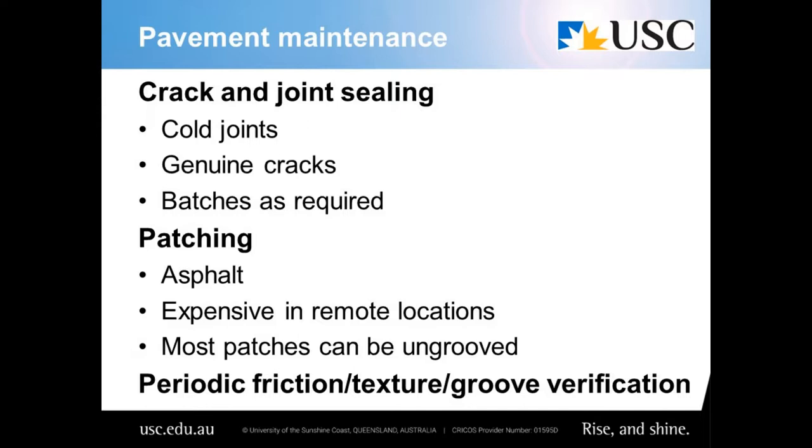As well as all that, there'll almost certainly be periodic friction testing for some verification that you've still got your surface texture. Depending on your asphalt mix, you might have a mix that gives you the texture without the need to groove, or that your grooves are still effective. And by effective, we really mean that they haven't collapsed or closed, that they haven't been eroded all the way down to their bottom, so their volume isn't sound anymore, or that they haven't been filled up with rubber or some other contaminant, preventing them from doing their job and allowing the water to get out from underneath the tyres as the planes go past.